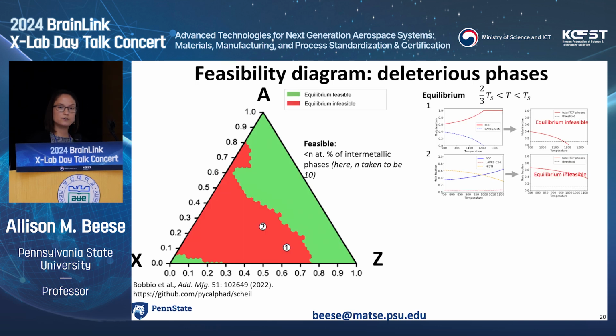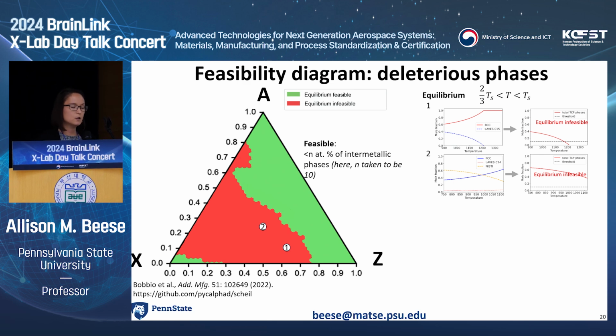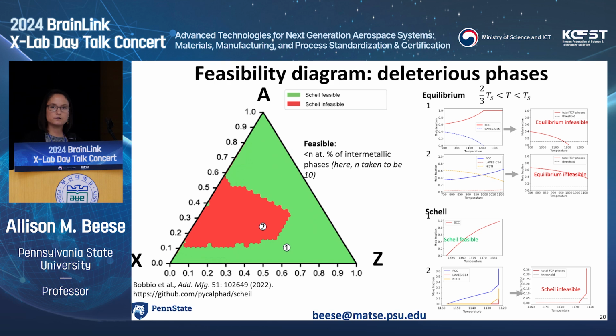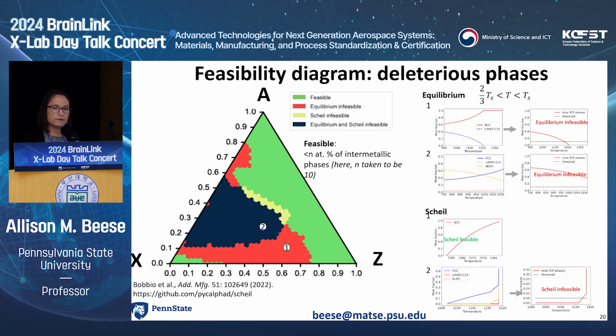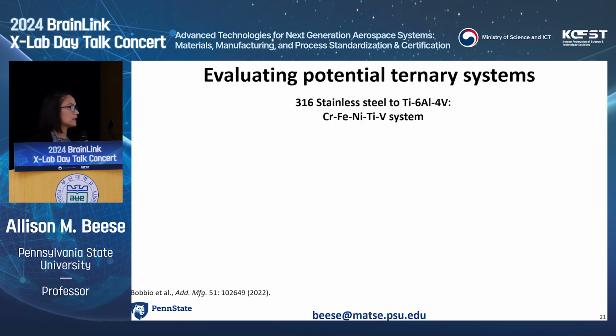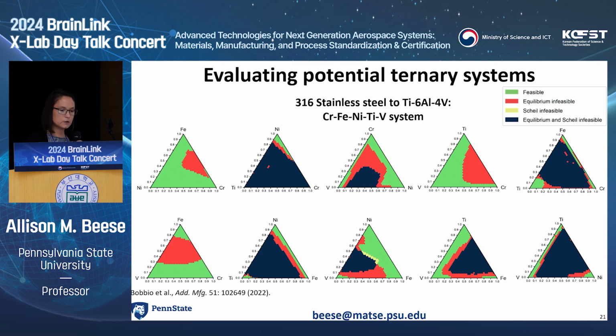If we take a look at equilibrium, which is relevant if we think about heat treatments after processing, or even some of the repeated thermal cycles that we see in additive manufacturing, we can then take a look at every composition and see if it's feasible or infeasible, meaning it has under or over 10% of intermetallic phases. And we do the same thing for Scheil. So Scheil is saying we have rapid solidification. What are our solidification products? And we stack those two together because those are our two extreme bounds. And we would say that we would only be interested in exploring this green space where we have a lack of intermetallics. And so to demonstrate this, we looked at this for grading a stainless steel to a Ti-6-4. So we take this simplified material system, and we can plot out all of the possible feasibility diagrams as shown here. So these are all of the ternary diagrams for that particular system.